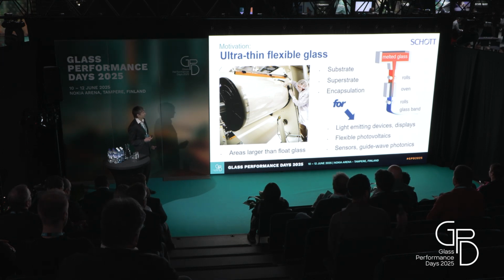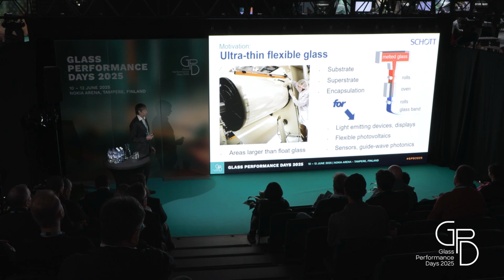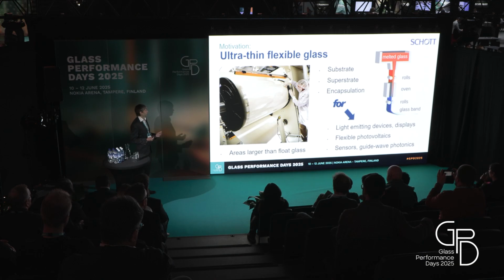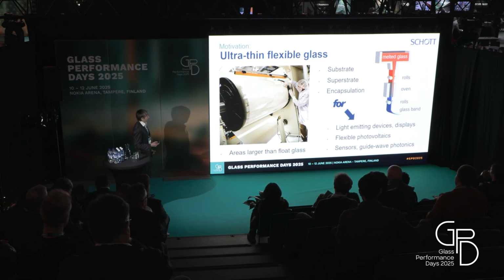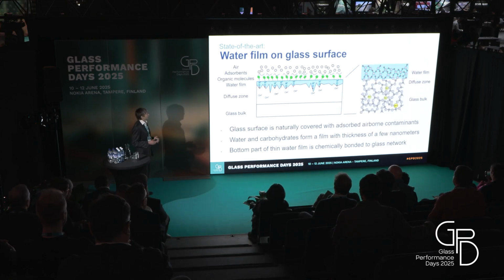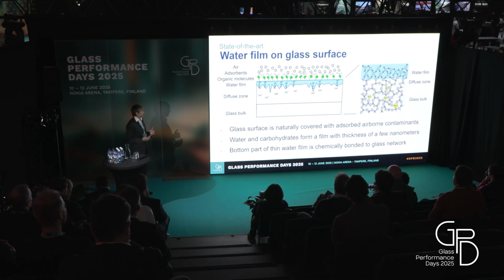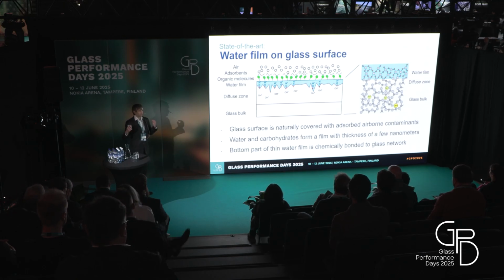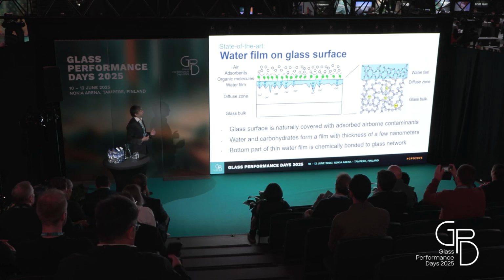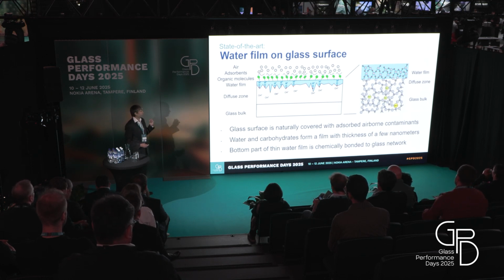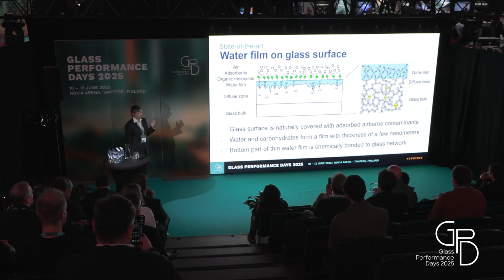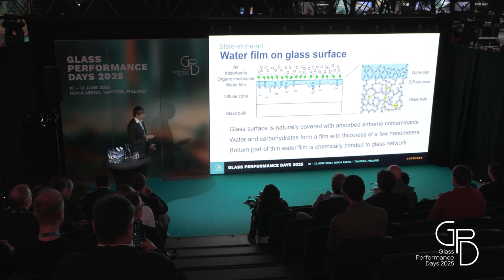Such flexible glass is interesting, for example, as an encapsulation material in electronics which need high transmittance, so optoelectronic applications like flexible photovoltaics and sensors. This flexible glass has a surface with a high surface energy, so it absorbs water and other contaminants from air, and it's covered with a very thin film, only a few nanometers thick, and this can hinder some coating applications which need to be bonded directly to the surface of glass or flexible glass.